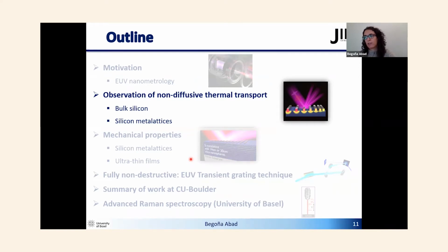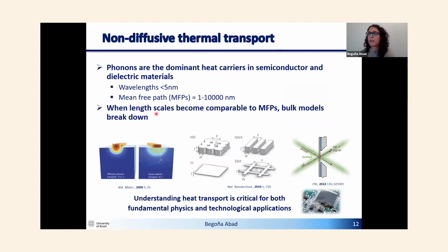So I will start talking about this non-diffusive thermal transport that we were able to see in both bulk silicon and silicon metalattices. This non-diffusive thermal transport is very important because it happens when the characteristic dimensions of the systems are on the same order as the phonon mean free paths. So phonons are the main heat carriers in semiconductor and dielectric materials, and the wavelengths are below 5 nanometers, and the mean free paths, as I said before, range from 1 nanometer to 10 microns.